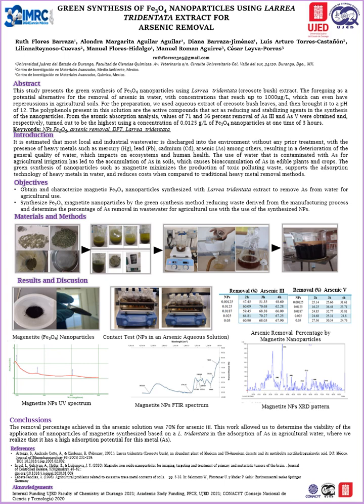3653.18, 1157.3, 1303.8, 741.15, and 582.5. The peak at 3653.18 is attributed to the presence of a phenolic group in the stabilization process.